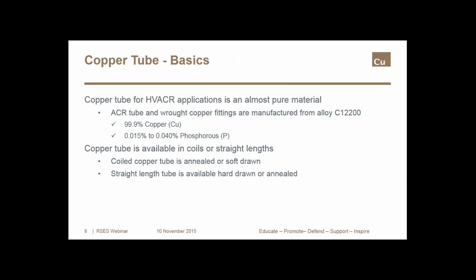Copper tube and fittings for air conditioning and refrigeration applications are made from nearly pure copper. It's an alloy we refer to as C12200, and it has over 99.9% copper with very small amounts of phosphorus. Copper tube is available in coils or in straight lengths. And if you're working with a coil, it's annealed or soft drawn. But if you're working with straight lengths, it could be annealed or drawn.